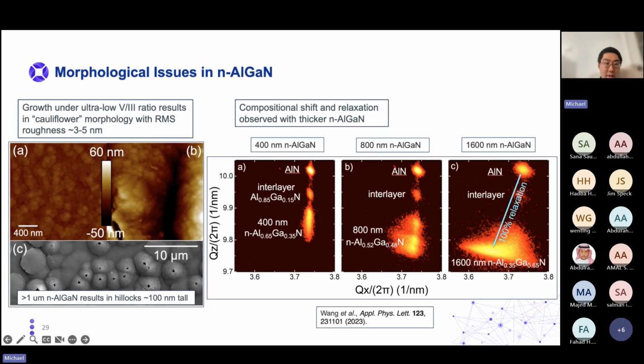Okay, sorry about that. So it results in larger than 100 nanometer tall islands with these holes in the middle. We can see these look like volcanoes, and this is definitely very detrimental to UV LED devices. You can't grow UV LED devices on this.